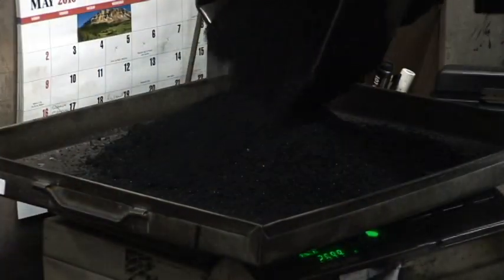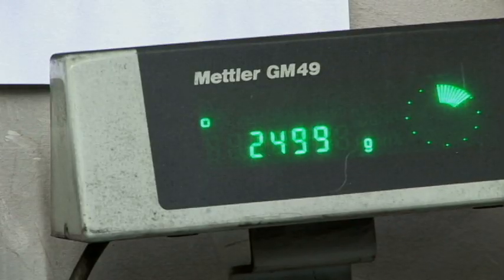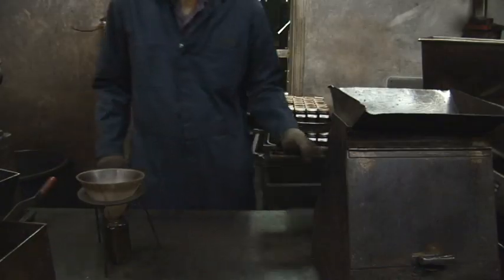The laboratory sample is then weighed and placed in air-dry ovens for required drying time. After a maximum of 17 hours, the sample is re-weighed for air-dry moisture loss. The sample is pulverized to specific sizing and placed in uniquely identified bottles, ready for the lab.